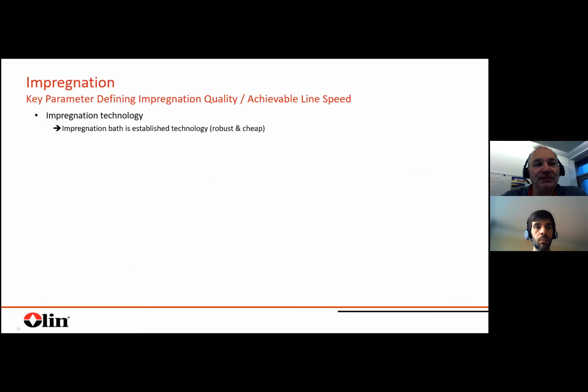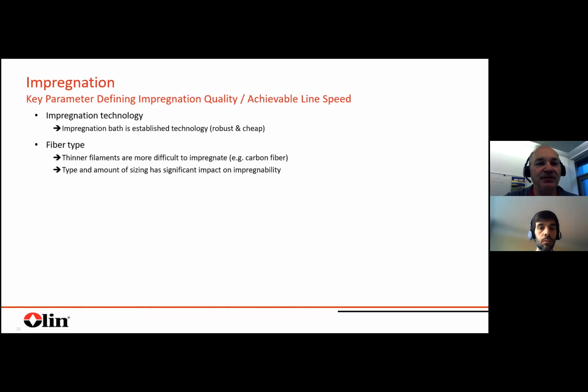So what are the critical parameters for the impregnation? So as mentioned, it's the impregnation technologies themselves. It's a simple bath. For other technical processes, transfer rollers or whatever are used. It makes probably not sense for all applications, but the technologies themselves and the resulting limitation are really some of the critical parameters for the impregnation. Fiber type, I think it's also clear. If you try to impregnate a carbon fiber, it's a different story than a glass, but also in between different glass types, for example. The sizing has a big impact, the quantity of the sizing. So it directly impacts the impregnability. And this has to be considered when you design your process and your part.